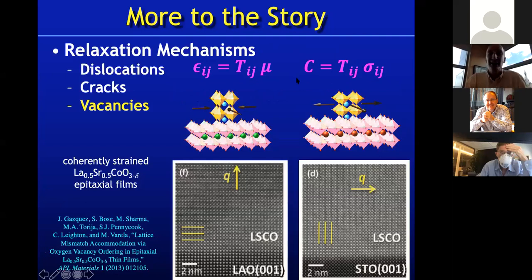In fact, in lanthanum strontium cobalt oxide, this is well documented in thin films, that if you try to play this strain game, as I'll call it, taking a substrate, in this case lanthanum aluminate, which has a smaller lattice constant than lanthanum strontium cobalt oxide, versus strontium titanate, which has a larger lattice constant, you can see a total difference in the defects that come about in this material.